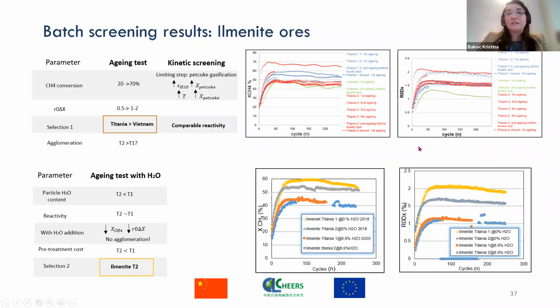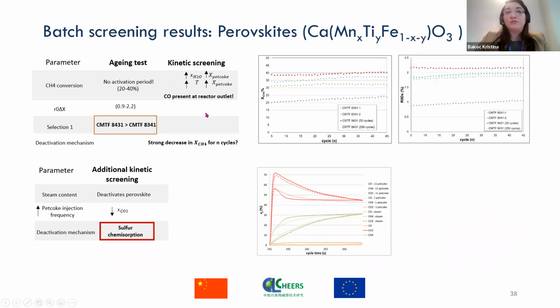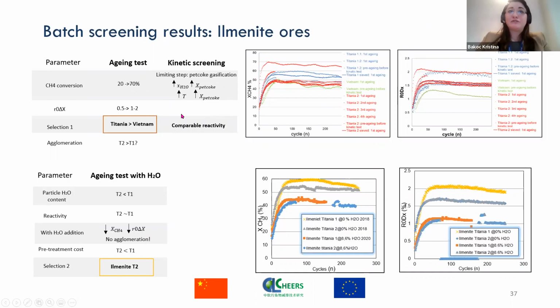Here, I give you the first results regarding the ilmenite ores. So following the batch screening, we found that ilmenite ores require a certain activation period, but after being activated, they achieve quite high values of conversion of methane, as well as this R0 delta X value, which means that the oxygen transfer capacity is quite high for ilmenite ores. As for the kinetic screening tests with Petcock injection, we found that they give satisfying reactivity, and in the conditions of higher water content or higher temperature, they would have better Petcock gasification. Out of all the ilmenite ores tested, Titania ore performed the best.